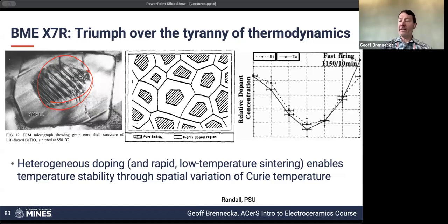What we can see with this is, we take this core-shell structure, we know that the boundary right between those is going to be right at the peak in relative permittivity. So that's the highest permittivity region, right where that boundary is. If we take this sample and heat it up, we will see the core gradually shrink as more and more of the grain becomes cubic. And as we cool it down, we'll get more and more of that core growing as a larger volume of the material is below its phase transition temperature.